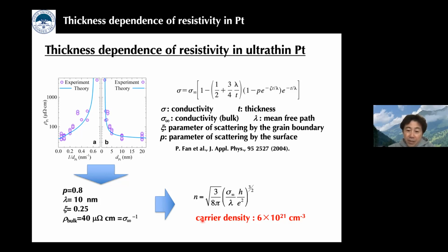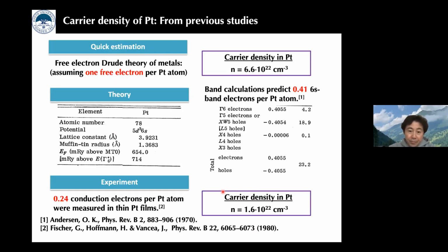In our estimation, the carrier density of thin platinum films is 6 times 10 to the 21st per cubic centimeter. Some of you wondered if the carrier density of platinum is very, very small, but it's not surprising. Of course, if we start from the conventional Drude theory, this means 1 free electron per platinum atom, so the carrier density should be 6 times 10 to the 22nd. But according to the band calculation, only 0.41 electrons exist per atom.